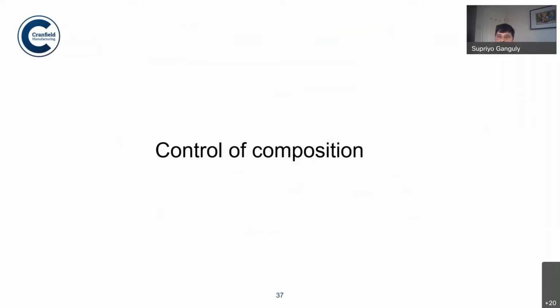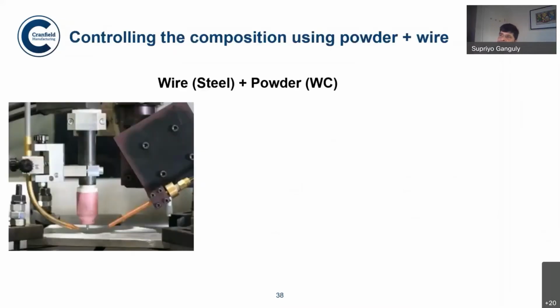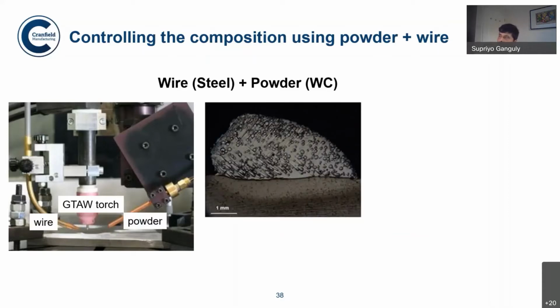Then the next area which I'd like to talk about is control of composition. Additive layer building gives us the unique flexibility of adding materials as we like. In this particular work, done by one of my students a few years back, we added tungsten carbide powder in the melt pool. This was done by a GTAW process, as you can see, and I am adding wire and also powder, and that gives us a composite structure which looks like this, which is very much acceptable to the industry for whom I was working at that time, from Cranfield. This is the structure which was produced.